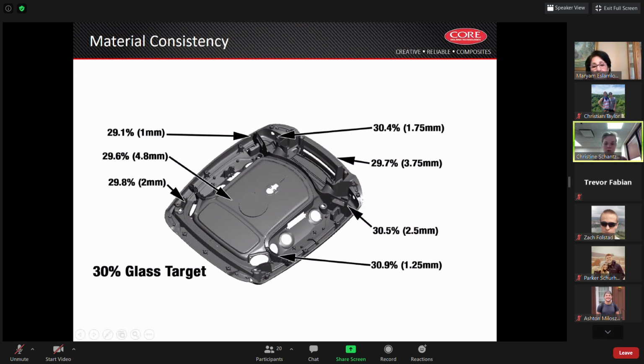So this slide just kind of shows that distribution of glass and material throughout the part. The numbers in parentheses on this slide, that's the thickness of that area. So you can see in the area on the top left side, that's 29.1% glass. That's a 1 millimeter thick rib. But even in that very small rib, it still has 30% of its content as glass by weight. And you can kind of see then the distribution throughout the part.